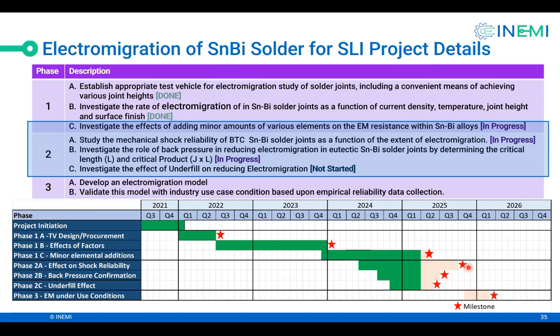So these are the 3 phases as I had shown before in the timeline chart. And this is just a much closer look. Here 1C is still in progress, with a couple of other solders that he's measuring for addition of minor amounts of various elements. And then we have a study on the mechanical shock for the BTC. This is important because as the bismuth migrates to one end, and bismuth being brittle, there is expected to be a drop off in the shock reliability. And so that's what we're going to be doing in 2A.